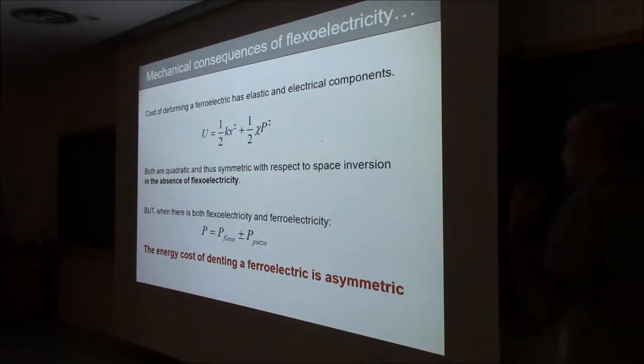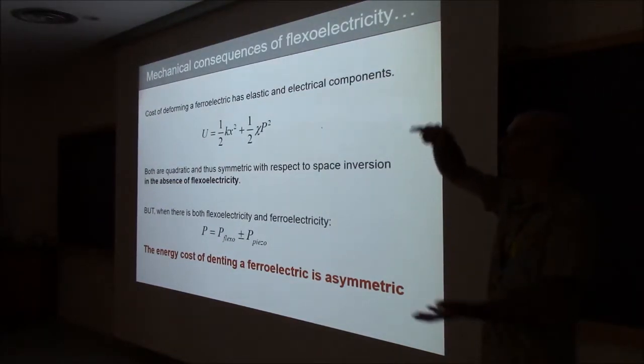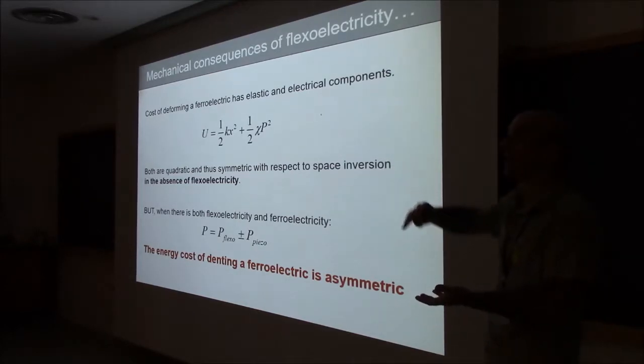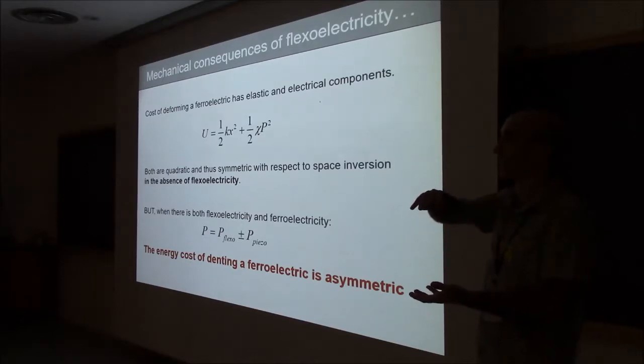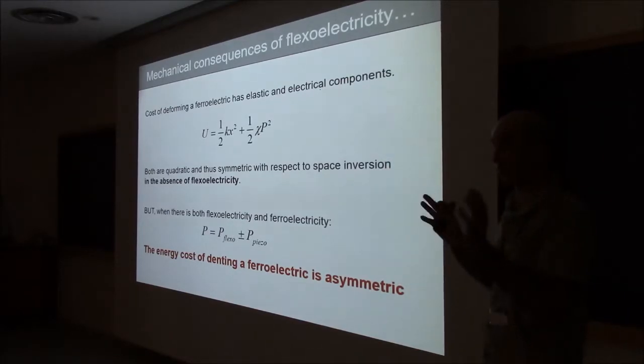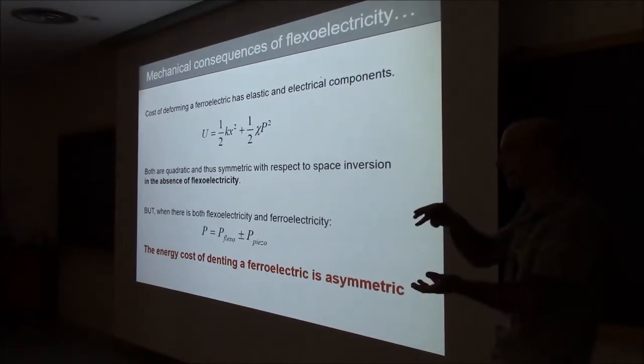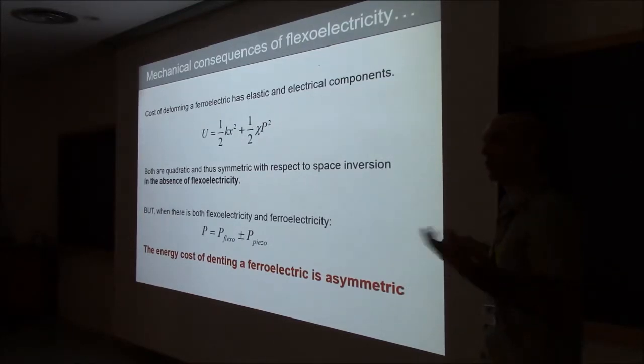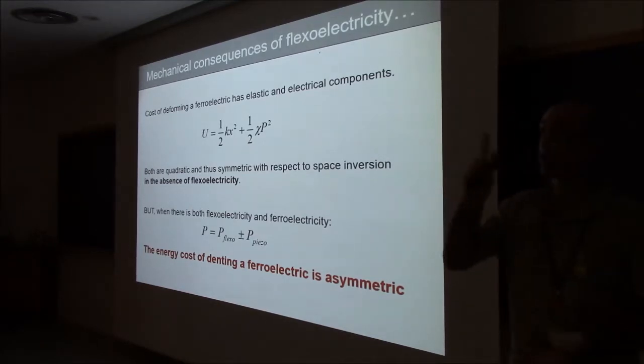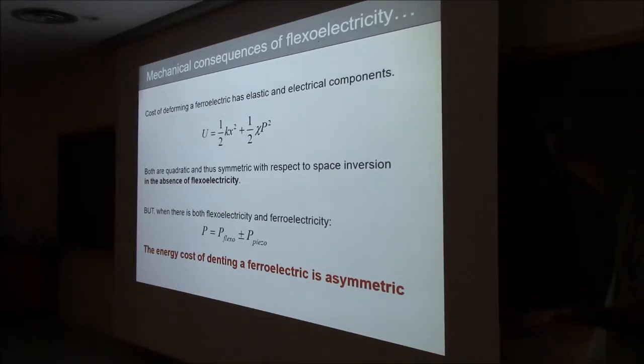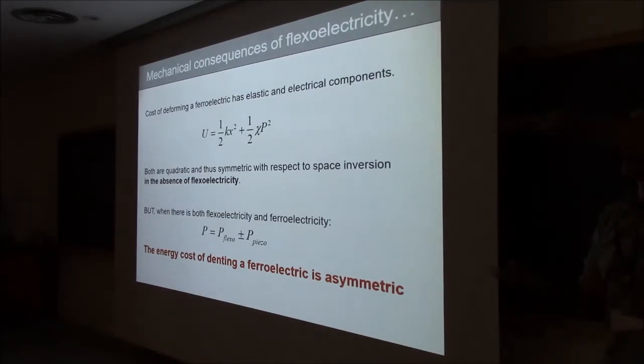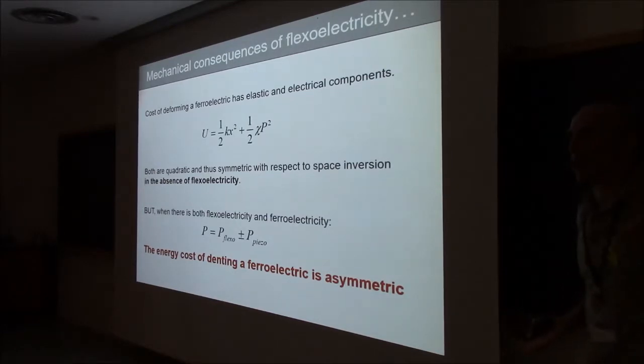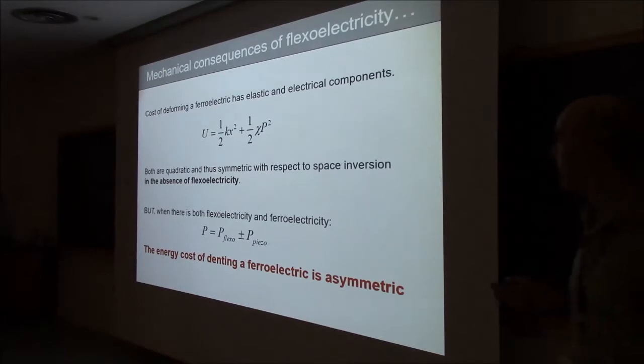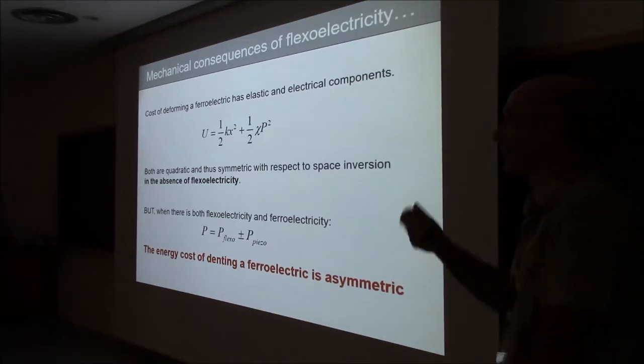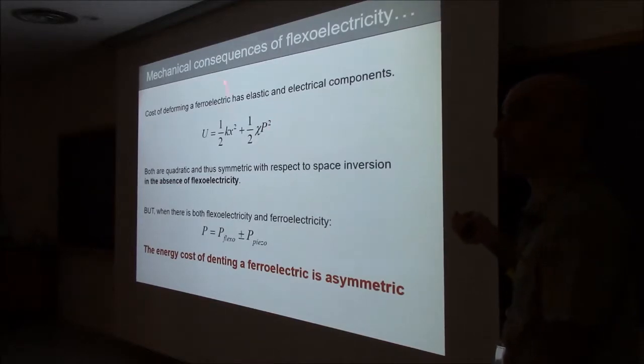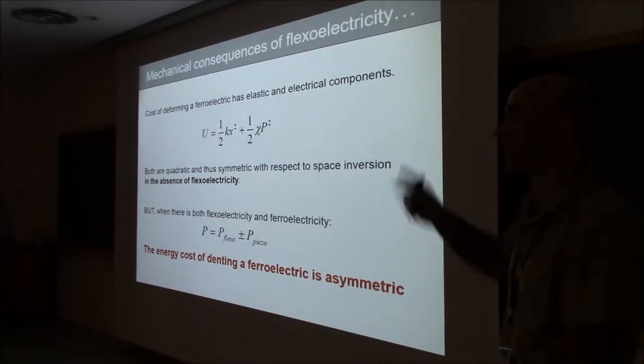So if you take a piezoelectric and you try to put some deformation on it, if you have no electrodes, you will see that it's actually more rigid than if it has electrodes and the two electrodes are connected. That's something quite funky, right? So the stiffness of your material does depend on how much polarization you create and how well you screen it. But it does not depend on the orientation. I can take the same piezoelectric crystal that was pointing like that, and I turn it upside down, and of course, the Young's modulus is not going to change. It does not depend on polarity. And this is basically because the stress, the strain, the elastic constant, everything here is given by even parity tensors, so tensors that do not change under space inversion.